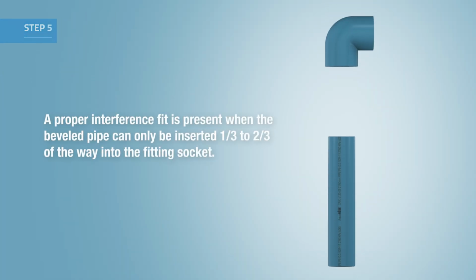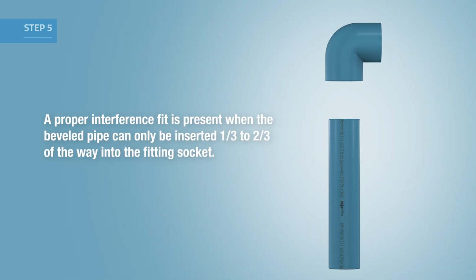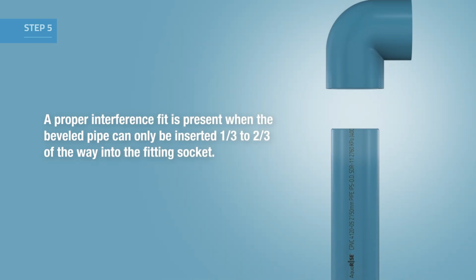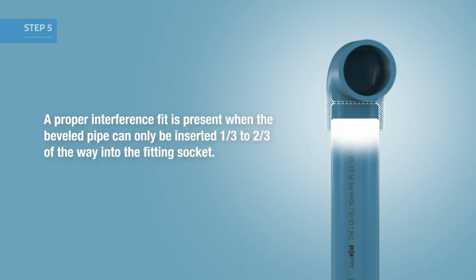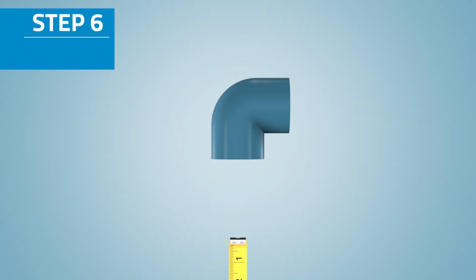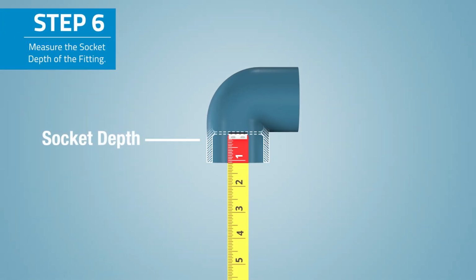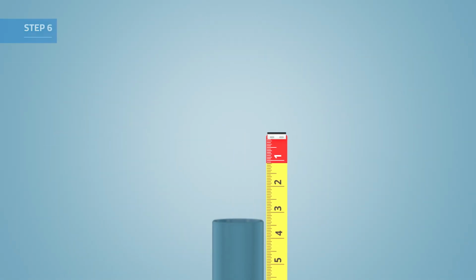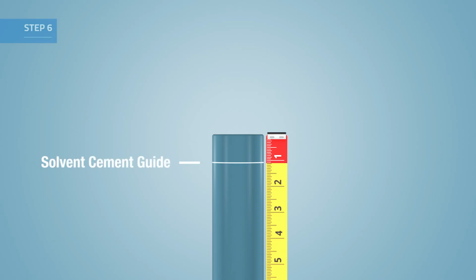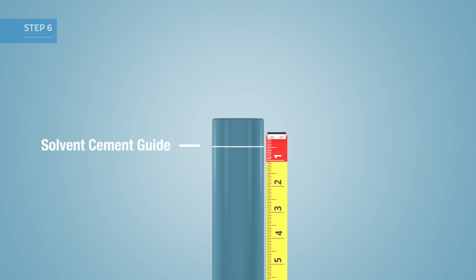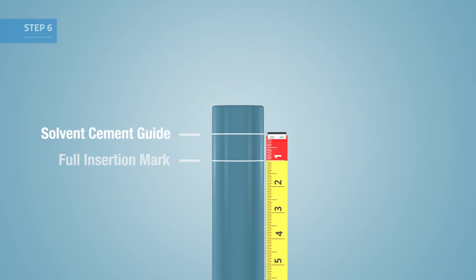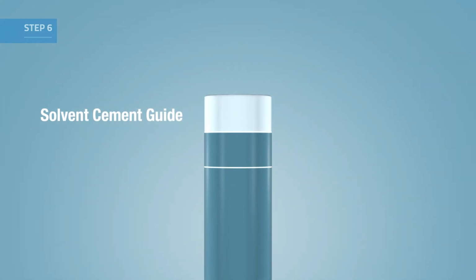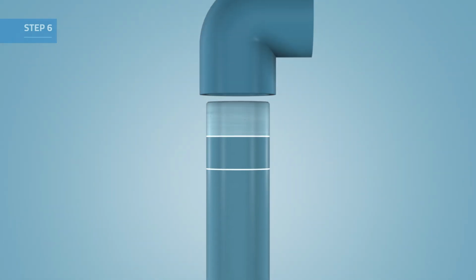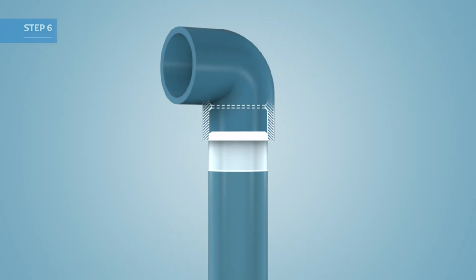A proper interference fit is present when the beveled pipe can only be inserted 1/3 to 2/3 of the way into the fitting socket. Step 6. Measure the socket depth of the fitting and mark that distance on the outside of the pipe. Then make a second mark 1 inch further back. The first mark serves as a guide for how far up the pipe to apply the solvent cement. After insertion, the second mark confirms that the pipe is fully inserted to the bottom of the socket.